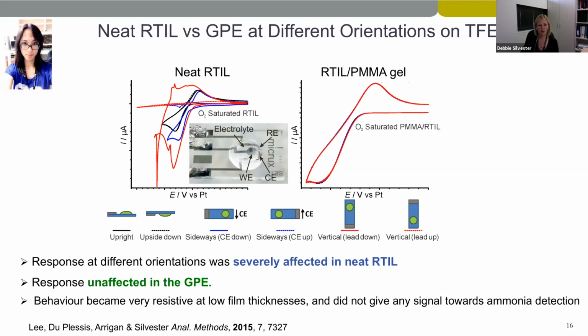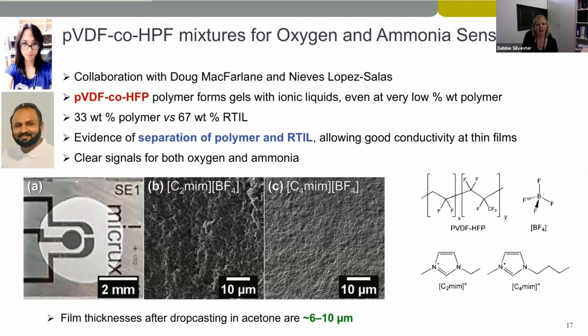So we were looking at other polymers, and in a conversation with Doug MacFarlane, we started a collaboration to use a PVDF-HFP polymer mixed with ionic liquids as a gas sensor material. So we used a roughly 1/3 polymer and 2/3 ionic liquid mixture.